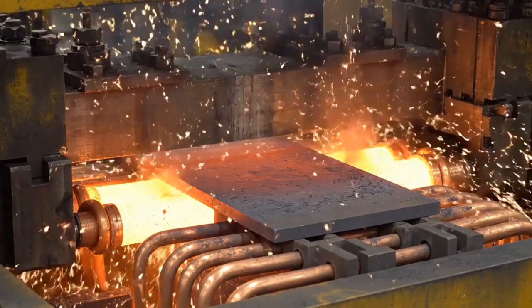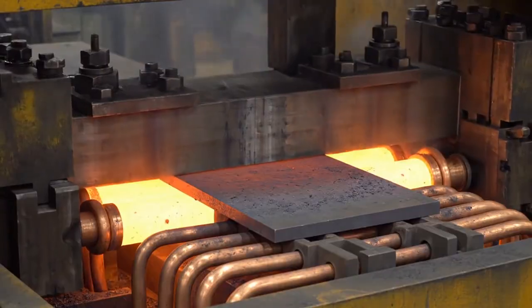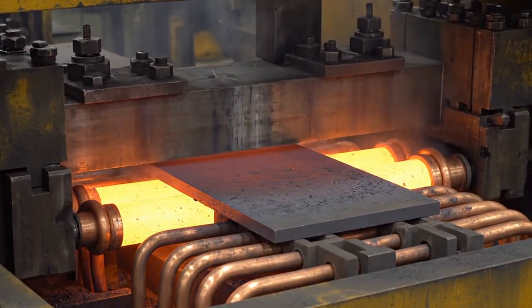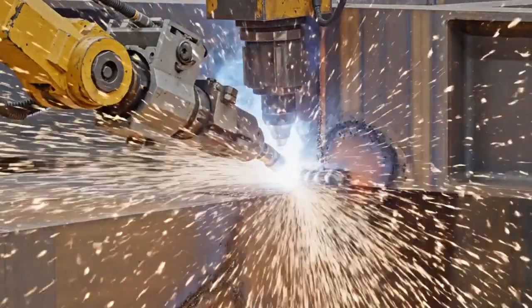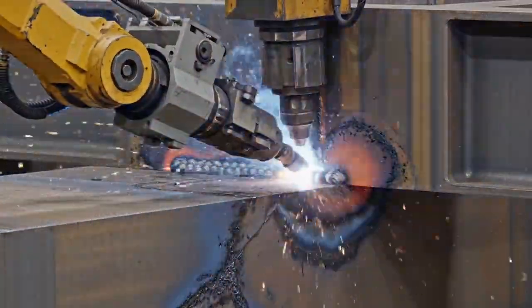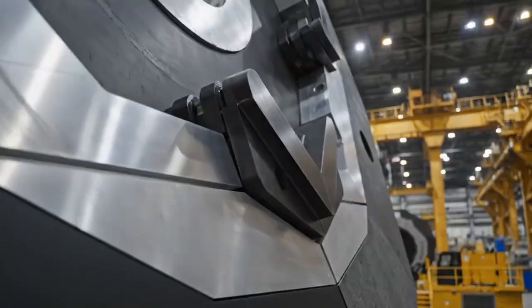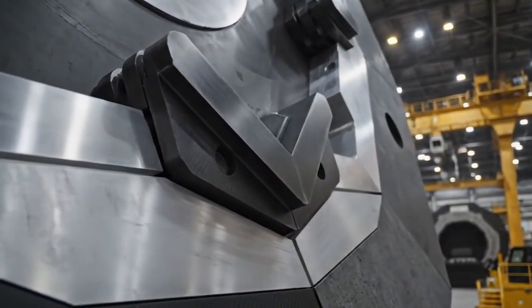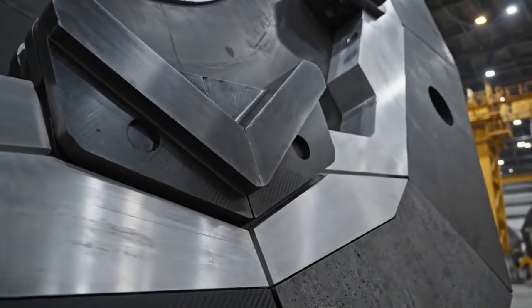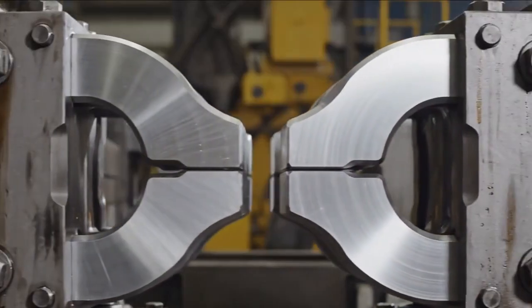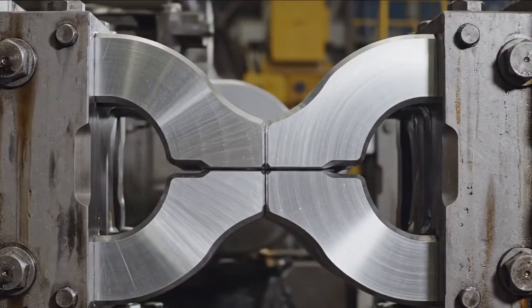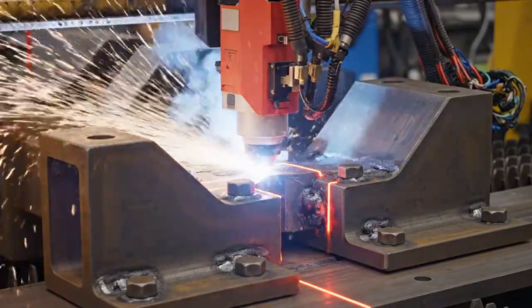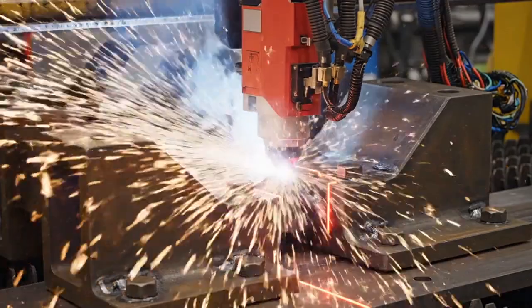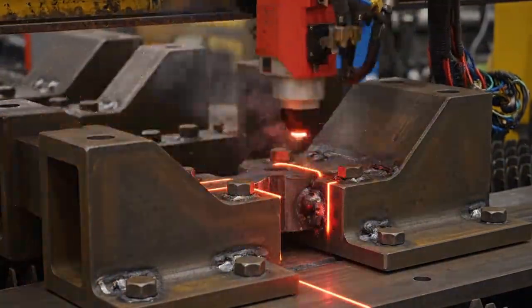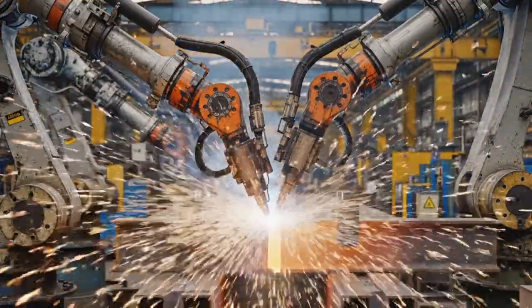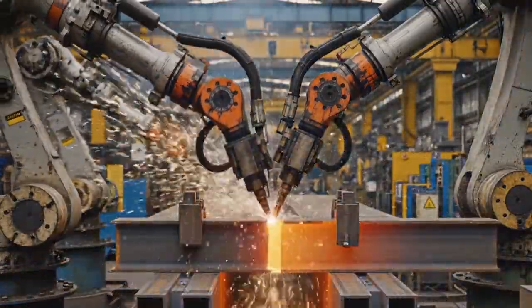Before the welding even begins, the high-strength steel plates are precision-heated using induction coils to optimize their metallurgical grain structure. The robotic articulators then lay down flawless weld beads across steel plates exceeding 100 millimeters in thickness. The engineering tolerances demanded here are ruthlessly strict. Despite the module measuring 50 meters across, the locking nodes must align with an allowed deviation of less than 0.1 millimeters. To guarantee this microscopic precision, continuous laser metrology scanners sweep the geometry of the steel brackets as they are welded, instantly adjusting the robotic arms to compensate for even the slightest thermal distortion.